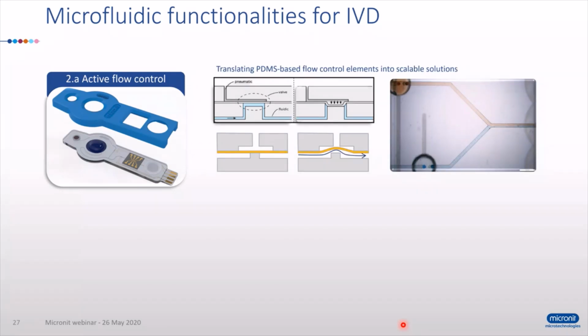Active flow control is known for a very long time, at least these kinds of valves, membrane valves or peristaltic valves. They are based on two rigid substrates that are microstructured with a fluidic layer and a pneumatic layer in case of pneumatic actuation, and a flexible layer sandwiched in between the two rigid layers. There are different configurations, normally closed or normally open, and you see them up here. I'll just take the normally closed to show what happens. In a normally closed valve at rest, the channel is closed, so there is no flow, and when actuating the membrane, for example by applying vacuum, thereby lifting the membrane, the channel opens up and the flow can continue.